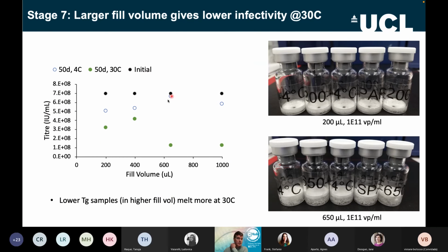And then hot off the press, this data came on Monday, so it doesn't yet have error bars on it, but these are the titers after 50 days incubation at 4 degrees and at 30 degrees, compared to what initially goes in. The titer you start with is in black across the top. These are the different fill volume samples being reconstituted and measured for infectivity. After incubating at 4 degrees for 50 days, you do see losses compared to what you start with, but it isn't nearly so bad as at 30 degrees, where you heat challenge it more.